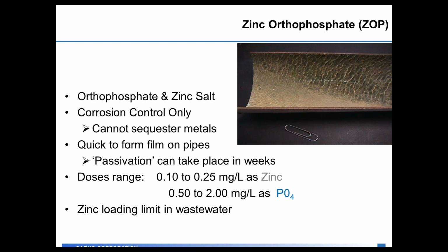Specifically, one of the orthophosphate products that's used is a zinc orthophosphate, commonly referred to as ZOPs. They're a combination of orthophosphate and a zinc salt, and they're used for corrosion control only because they do not contain any polyphosphate, which would be used for sequestering of metals. The reason zinc orthophosphates were used was they were very quick to form a film on the inside of the pipe. That's a piece of copper pipe with a zinc orthophosphate film forming on the picture that you see. Passivation would take place in weeks, so you would feed the zinc orthophosphate at the water plant and that film would form very quickly out in the distribution system.